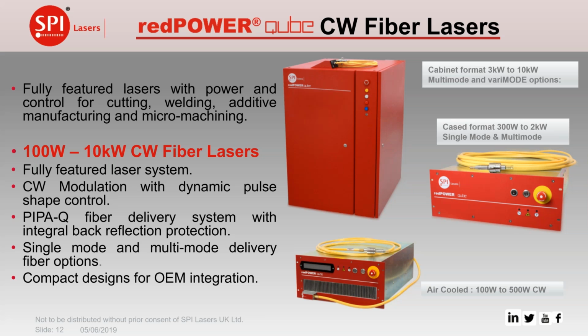And for the SPI lasers, we have a proprietary type of fiber connector, we call it the PIPA-Q, which is mechanically compatible with some of the industry standard Q-type connectors, but is different in that it has an integral back reflection protection built into the termination of the fiber. So we're able to deal with back-reflected light from those highly reflective materials like aluminium and copper, and deal safely with the reflected energy right at the end of the fiber rather than waiting for it to get somewhere into the laser, where we do have some backup systems as well. It's a very flexible range, it's very good control, and as we'll see, works well even in these oscillation welding applications.